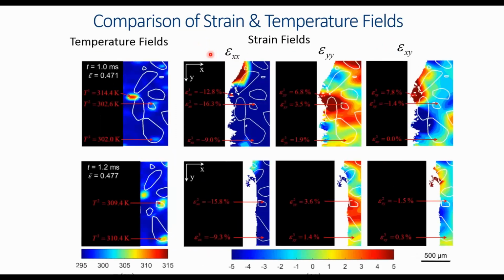This is the digital image correlation result obtained there, with the temperature fields here and the strain field here, allowing us to study those hotspots here at 1 millisecond and 1.2 milliseconds. It was seen in this example that the temperature increase in the hotspot was accompanied by an increase in the shear strain in the hotspot, and the conclusion is that the two main mechanisms in the material are plastic deformation and friction, both of which result from shear deformation beyond